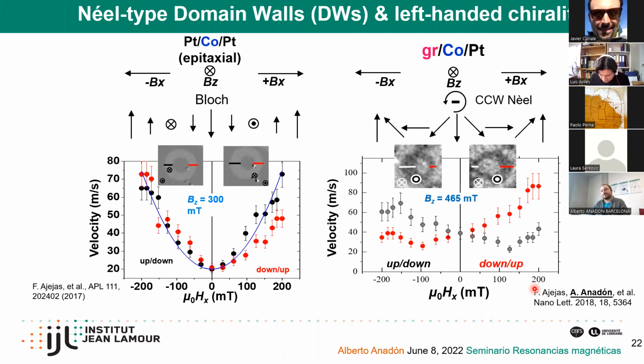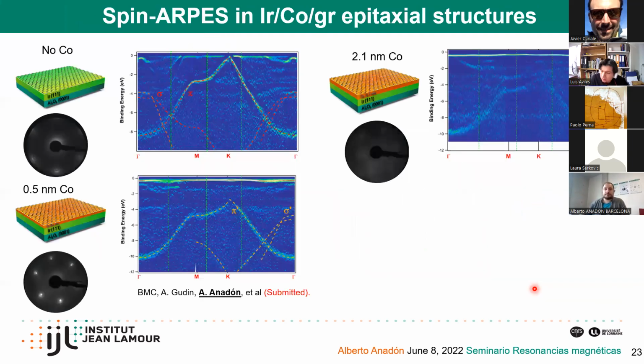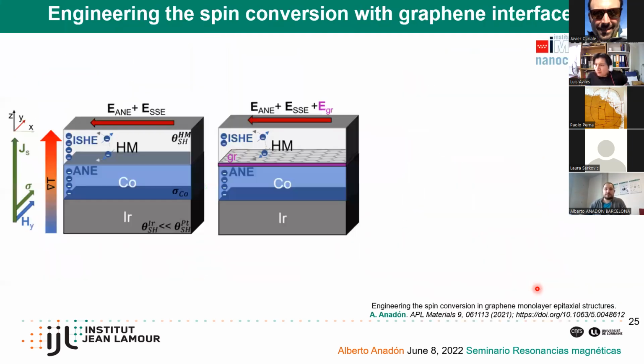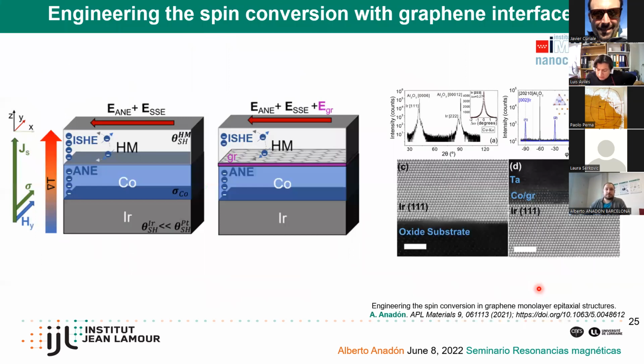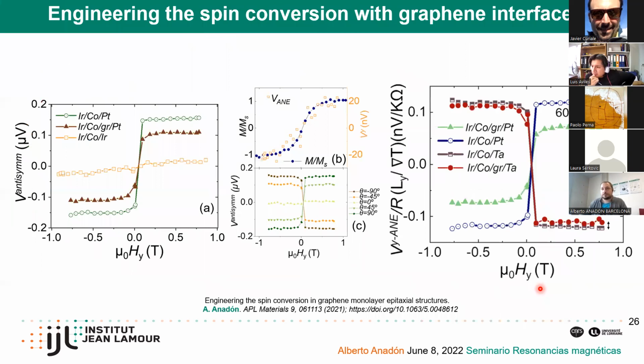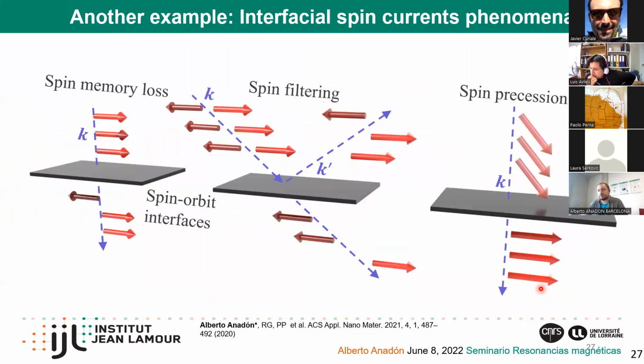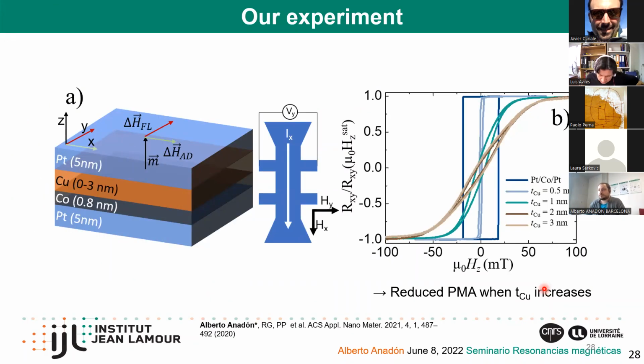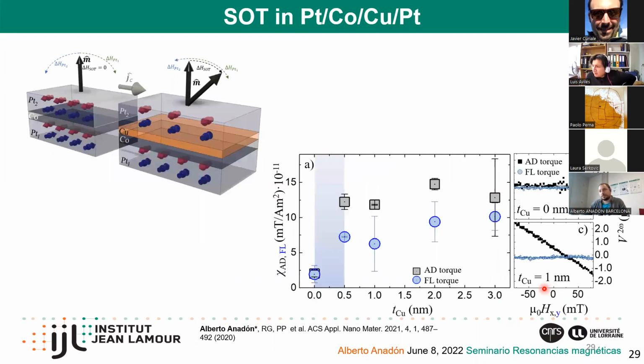I have a question also. In the measurements of SOT in platinum, cobalt, copper, and platinum, you show that you have a transition from out of plane to in plane magnetization, but that is not reflected in your results. In the next slide, you are not able to see any influence of the in plane to out of plane. Yeah, in that one.